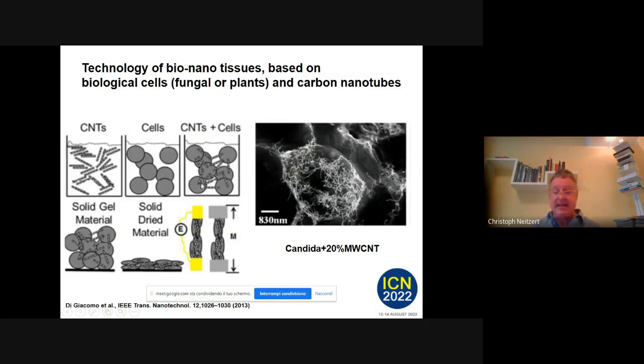So just the last I'll show, we use not only classical matrices, we use bio-nanotissues. We made bio-nanotissues by combining carbon nanotubes with biological cells, mixed them. Then they were combined in some way. The recipe you can find in this publication here from about 10 years ago. We dried it, and then we made again electrical contacts or mechanical contacts. We wanted to measure the mechanical properties and the electrical properties of this new kind of bio-nanotissue.